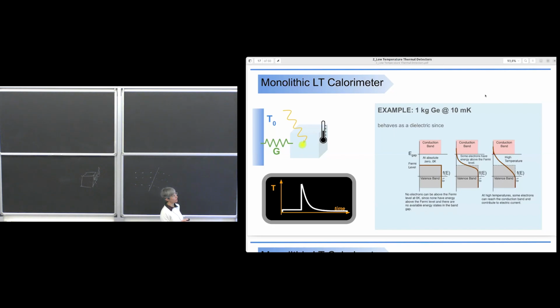electrons at that temperature allows some electrons to move from the valence to the conduction band, being excited by thermal fluctuation. This is no longer true when you decrease the temperature, because the energy distribution of electrons is moved down toward the valence band. At 0 Kelvin, everything is completely frozen. So germanium at low temperature behaves as a dielectric. This also means that all standard electronics and standard sensor devices do not work at 10 millikelvin, because they are all based on semiconductors. So you have to design a new kind of sensor.